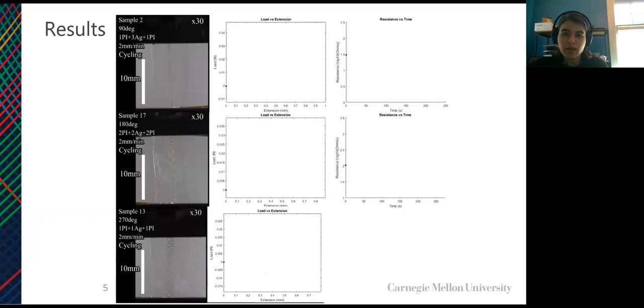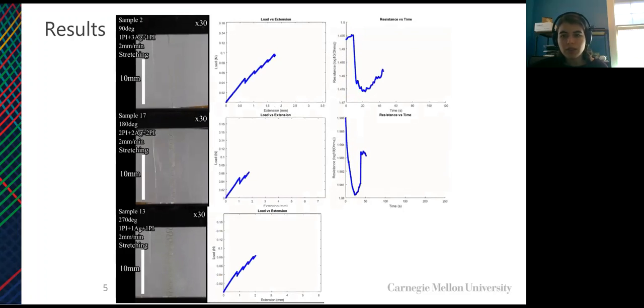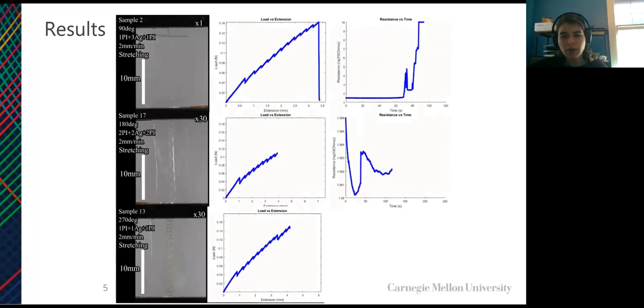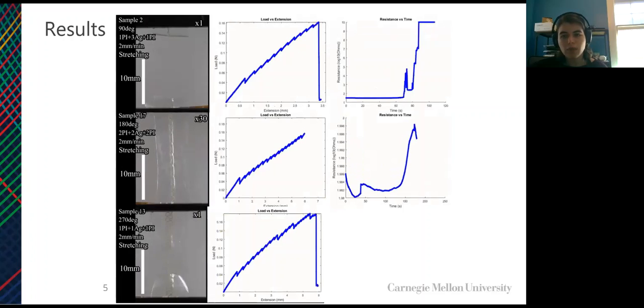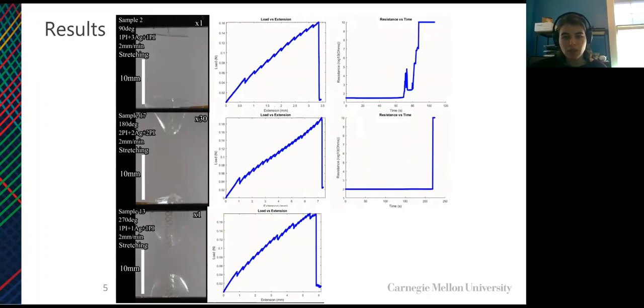Once fabricated, the samples were then tensile tested in an Instron machine and stretched at 2 millimeters per minute. These videos show the real-time load versus extension and 2-point resistance with time plots as the sample is being stretched. From the load versus extension plots, you can see a sawtooth pattern, which is possibly due to the cleavage failure occurring between the polyimide and PDMS at different points across the serpentine.